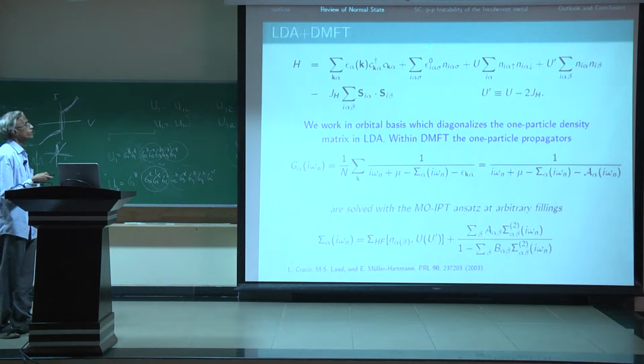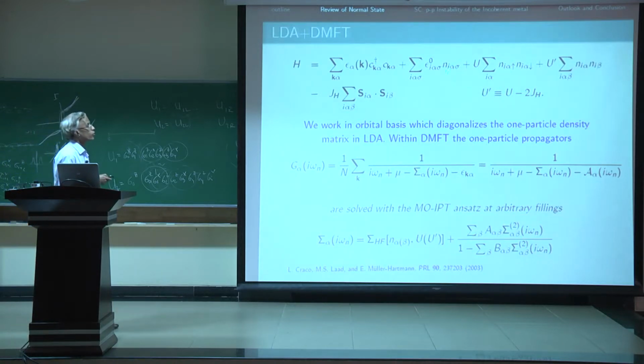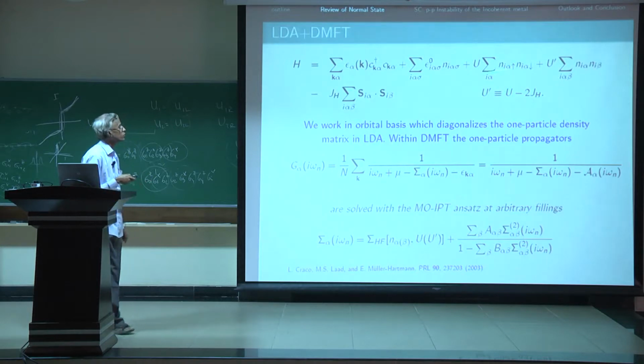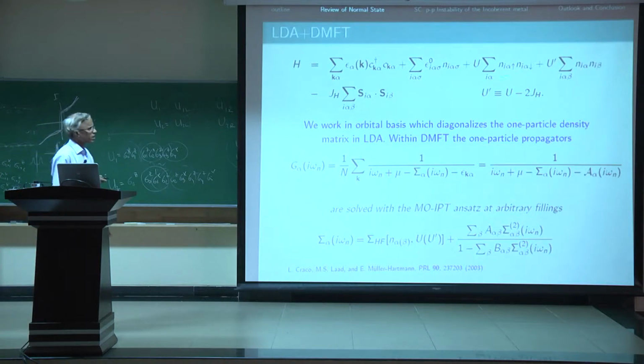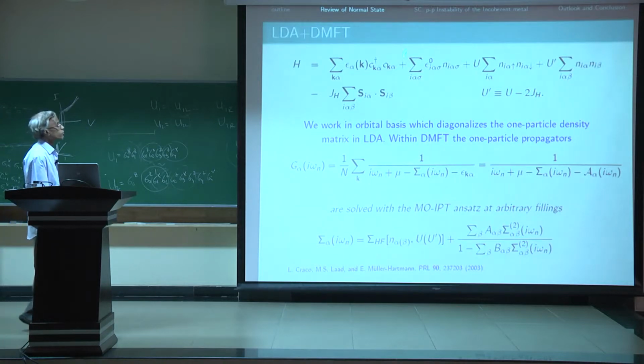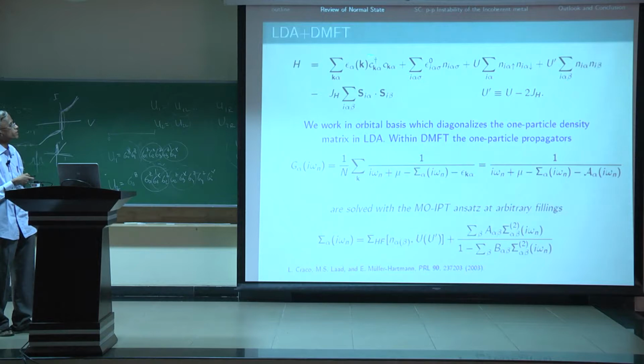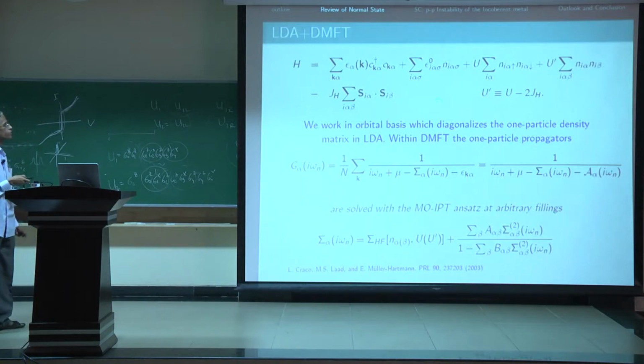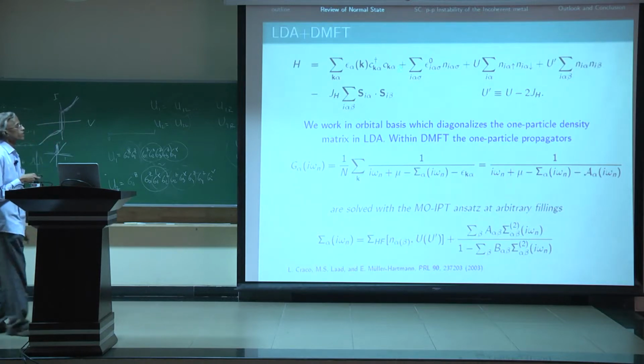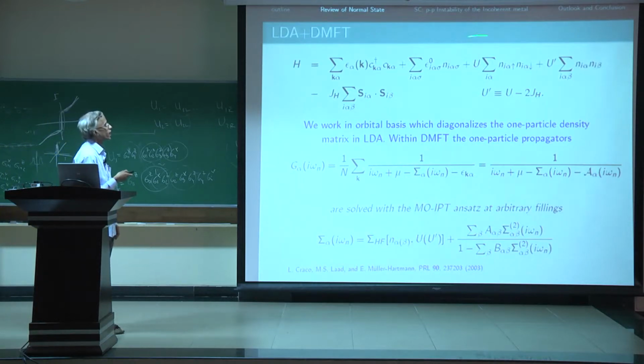This is the on-site orbital energy of the 5D states. This is the local Hubbard U, intra-orbital Hubbard U, inter-orbital Hubbard U, and the J Hund, which is basically approximately related to the rotational symmetry on a single ion. So furthermore, to simplify things, we work in a basis which basically diagonalizes the one particle density matrix in LDA. So that simplifies things because one can work with matrix propagators which have elements which are the diagonal elements are the most dominant and off-diagonal elements are small. In the absence of that, this whole scheme just becomes terribly complicated.